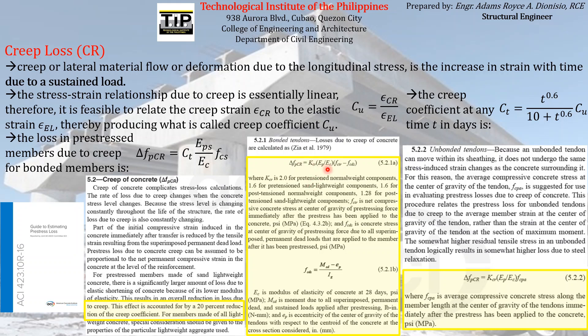If we investigate the formula for bonded tendons for finding the pre-stress loss due to creep, it is composed of the product of the creep coefficient KCR, the modular ratio — the ratio of the modulus of elasticity of pre-stressing reinforcement to the concrete — and the difference between FCIR and FCDS. FCIR is the net compressive concrete stress at the center of gravity of the pre-stressing force immediately after the pre-stress has been applied to the concrete. FCDS is the concrete stress at center of gravity of the pre-stressing force due to all superimposed permanent dead loads applied to the member after it has been pre-stressed.